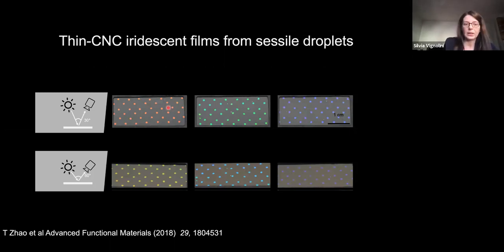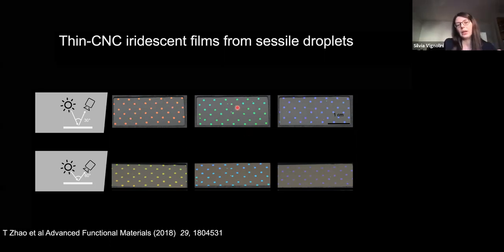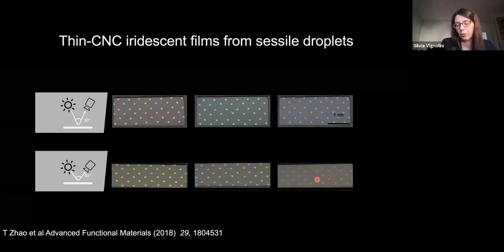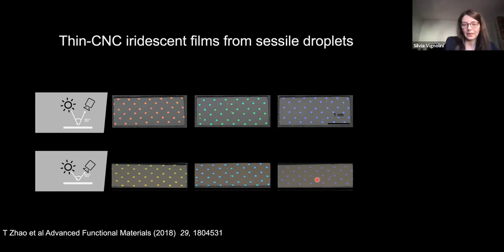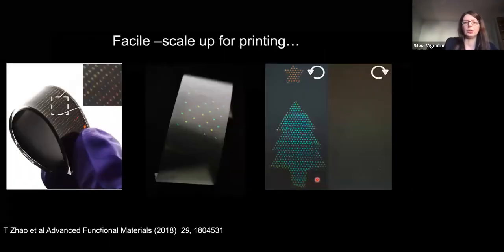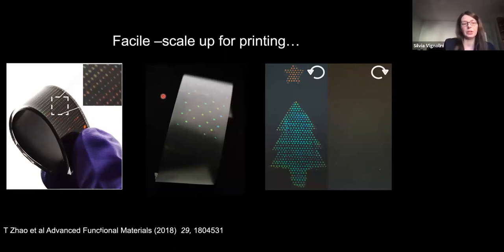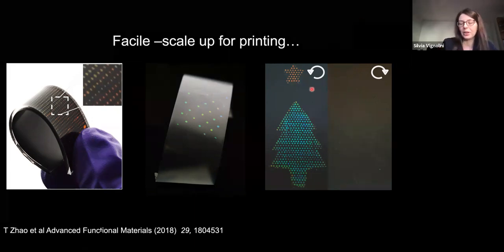The way it works, if you have a red structure and you tilt it, it looks kind of yellowish green. When you look at green, it goes into the blue, and when you do it with blue, it shifts into the ultraviolet, which we are not able to perceive with our eyes. But it will reflect in the UV region. And these printing techniques are pretty cool because you can then transfer them, you can print on different types of substrates. And what I think is very nice is that since you have this structure which is chiral, I didn't go too much into detail, you can also use it as a security feature. In fact, not only do they interact with light, but they also interact with the polarization of light.